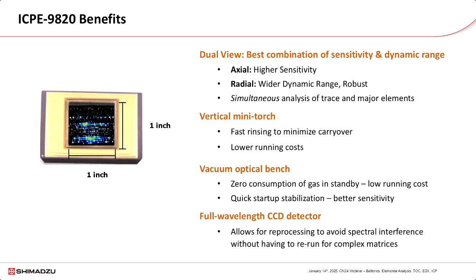The Shimadzu ICPE-9820 is also equipped with a CCD detector that captures all of the wavelengths from 167 nanometers to 800 nanometers in one exposure. This allows for reprocessing of data to avoid spectral interference without having to rerun for complex matrices. For example, when you analyze one element at a certain wavelength, during data reprocessing, you realize that the wavelength you selected at the beginning suffers from interference and is not the best one to use. In this case, you do not need to rerun your sample.